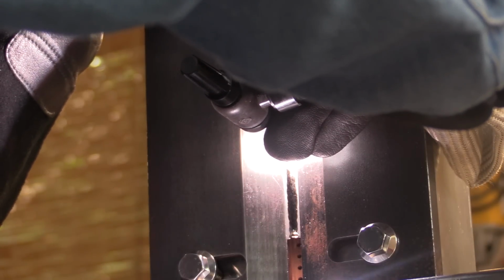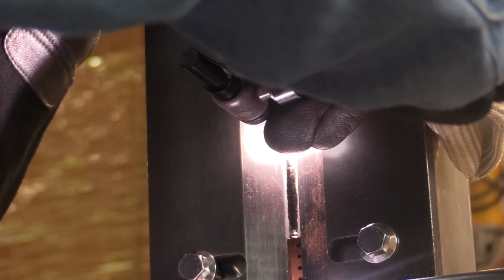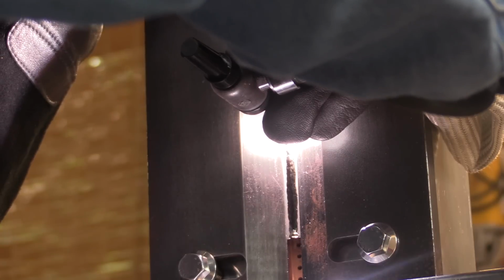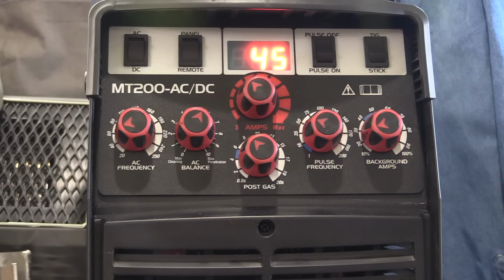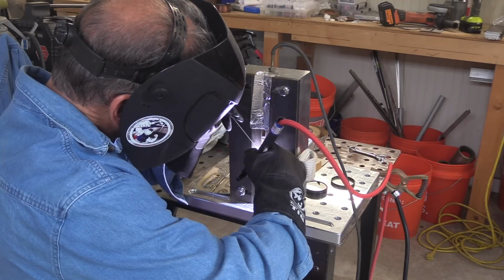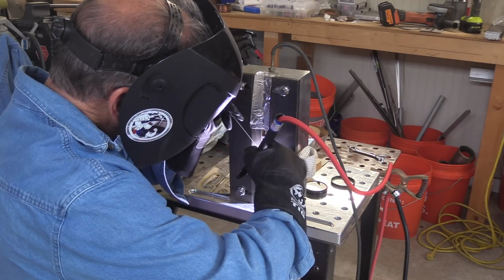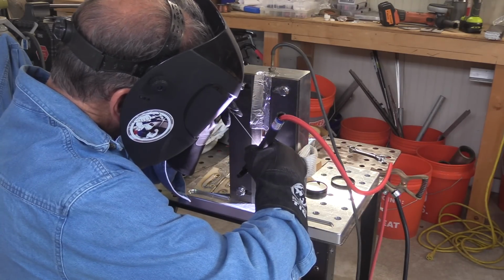It looks like the cup is doing a pretty good job of shielding. Got a nice silver weld trailing there. I'm running about 45 amps here. That's going to depend on your travel speed and how far you have the chill blocks put in there and some other things. Somewhere between 40 and 45 amps though.